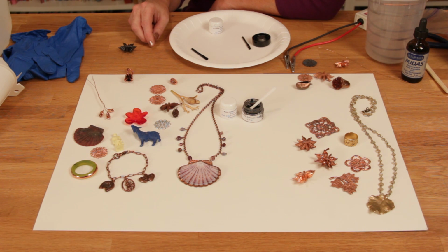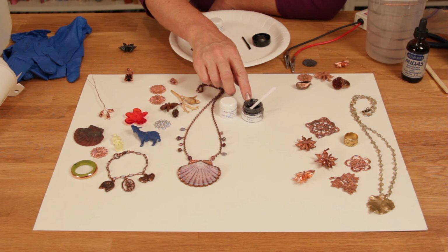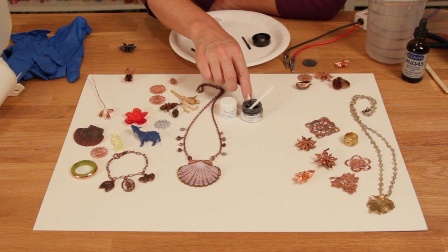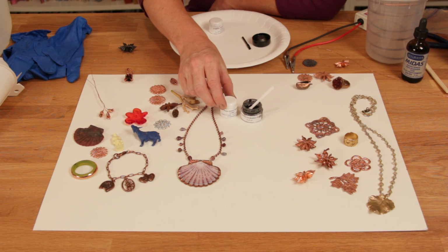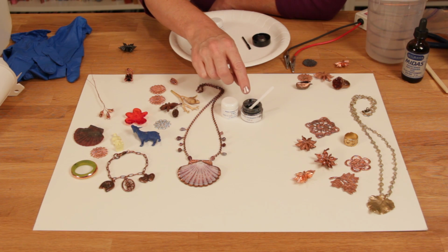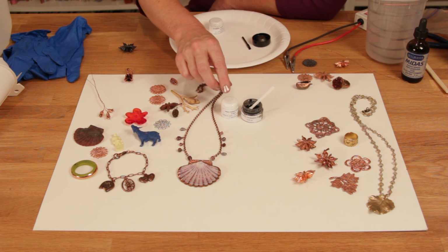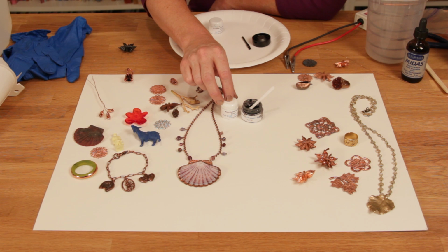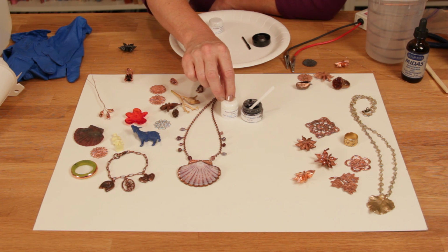Before you can electroform an object, you need to prepare the surface and also make it conductive. We like to use graphite paint, which will make the surface conductive, and that helps the copper know where to plate. And then some surfaces need to be prepared with a varnish prior to putting the graphite on the surface. And the varnish will help seal organic materials and keep them from contaminating the solution or disintegrating during the process.